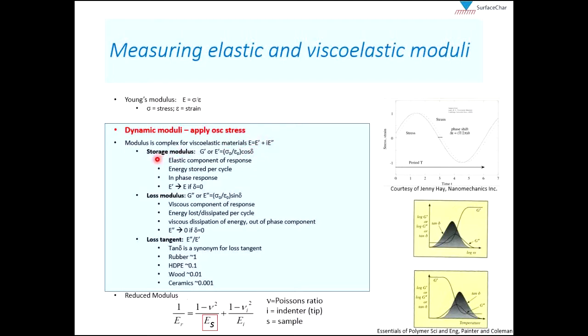The real part we refer to as a storage modulus. That is called either G prime or E prime, where this letter simply refers to how that oscillation is being applied. So G, it's in shear, and E, it's in tension. And it's simply equal to the initial stress over strain times the cosine of this lag, delta. The storage modulus is the elastic component of our response and refers to the energy stored per cycle in oscillation. And note that if this lag is 0, the storage modulus simply goes to our static elastic modulus.